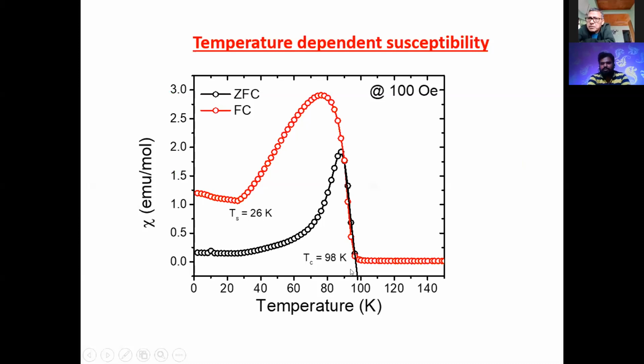At a certain point, the ZFC and FC curves travel in different directions. But the FC curve, in one certain region, suddenly increases. That region is called the conical spiral spin transition, and that temperature is called the spiral transition temperature. It is observed around 26 Kelvin. Field dependent magnetization.